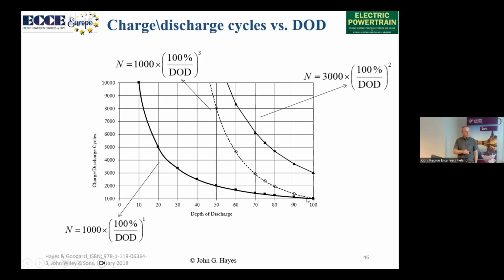Then the simple thing was, well, what if I only discharge it 50%? Then we'd get 2,000 cycles. If I discharge it 10%, we'd get 10,000 cycles. And there was a view that it had a constant energy throughput. So the less I do, the more cycles I get. Talking to the folk in Detroit many years ago, they're saying, no, we're far better than that. Maybe it's 1,000 cycles at 100% depth of discharge, but if we go to 80% depth of discharge, we could probably get 2,000 cycles. If we go to 50% depth of discharge, we can probably get about 8,000 discharge cycles. So now we're into great territory because there's only so many charge-discharge cycles we can impose on our vehicles.